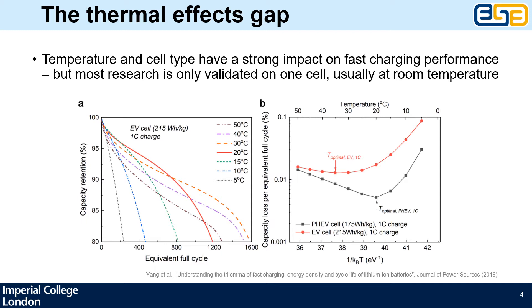The fact that temperature very strongly affects battery behavior is already well known. In the case of fast charging, we generally aim to reduce degradation by minimizing the rates of two main side reactions that take place on the graphite anode: the growth of the passivating SEI layer, which is accelerated at high temperatures, and lithium plating, which is favored at low temperatures and high charging currents. Lithium plating is particularly problematic because when it does happen, it tends to be much faster than SEI growth and can potentially lead to internal short circuits or at least rapid capacity fade.